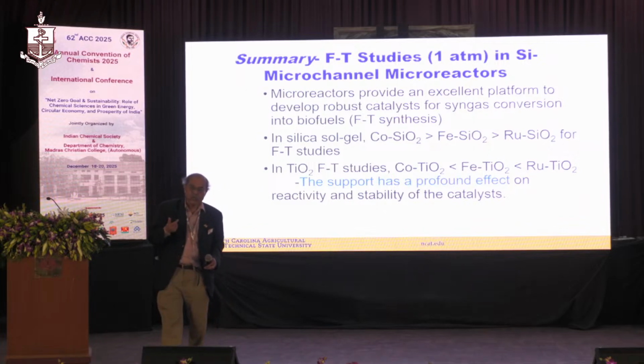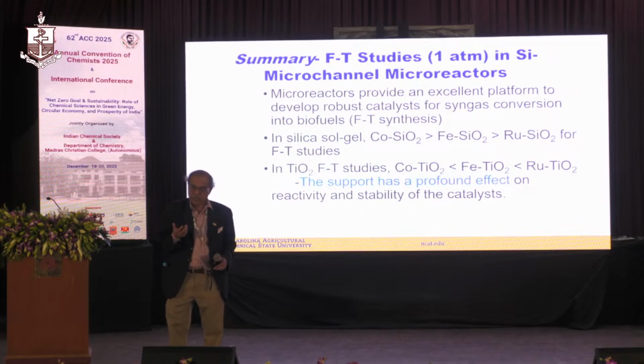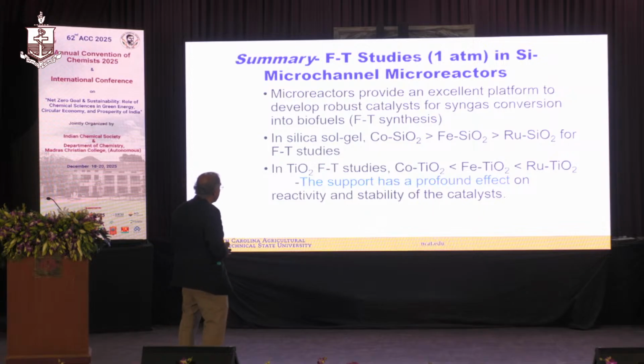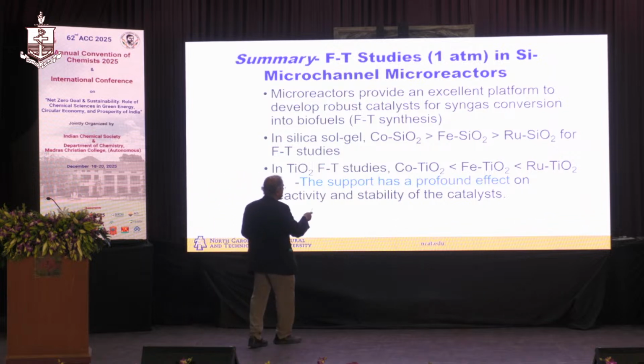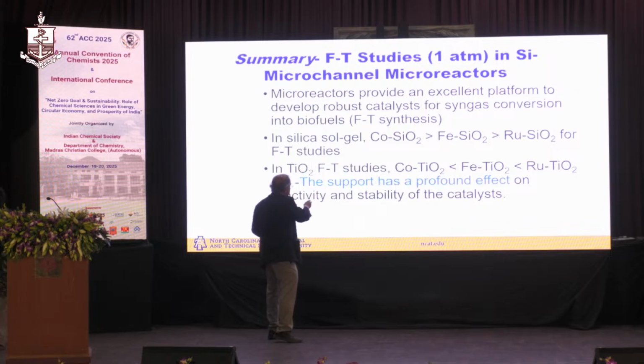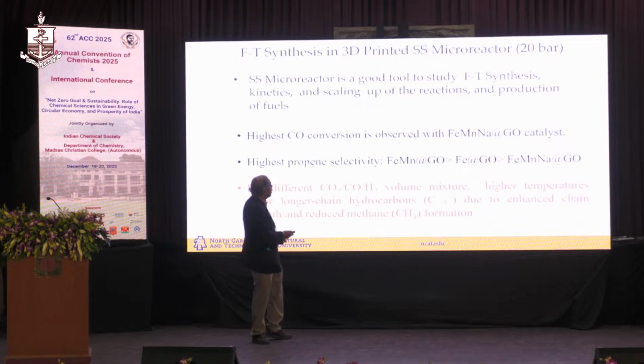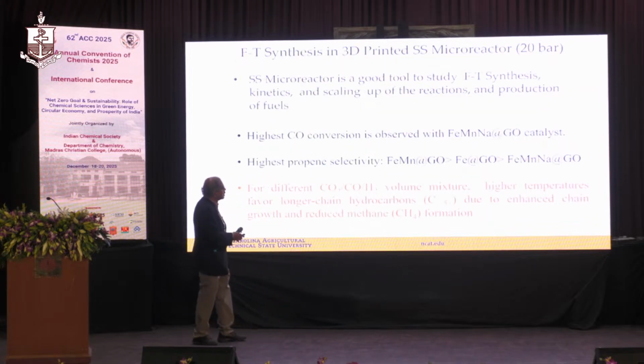I first told you about Fischer-Tropsch synthesis using a 3D printed stainless microreactor. I took you quickly through the silicon-based microreactor, and how we moved into this. In the silica sol gel, cobalt and iron are better than ruthenium. If you go to TiO2, everything changes. Then you can use a promoter like manganese or manganese sodium, add it to the iron, and you can see the propene selectivity increases.